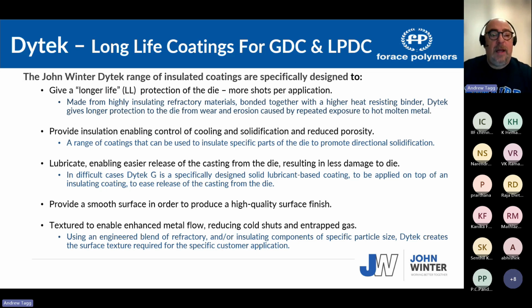Also, some additional coatings could be used as lubricants, sprayed on top of an insulating coating. There's also use of primer coatings, like you would normally do on a building, where you put a primer on, then put a top coating on. So die coatings have specific coatings for specific applications, and they play a significant role in productivity. The life of the die coating obviously significantly affects productivity, because if the coating fails, then you have to take the die off the apparatus, and that's lost production.